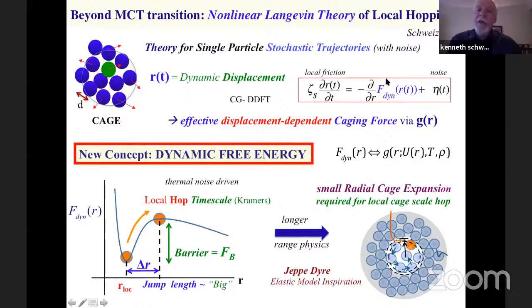And so this quantity then we call the dynamic free energy. Its negative gradient is a force. And that's a new concept that's now been around for a long time. It's not new in that sense. The form of this beyond the mode coupling transition is this. It has this form that's sketched in blue as a function of displacement of a particle. So if a particle has a trajectory on this, it moves, it gets trapped at a distance we call the localization length. And then through random fluctuations, it ultimately surmounts the barrier with a jump distance that's predicted and a barrier that's predicted. And identification of the mean time scale for this using Kramers' theory is identified with the alpha time.